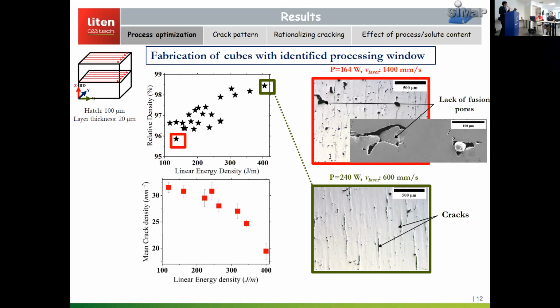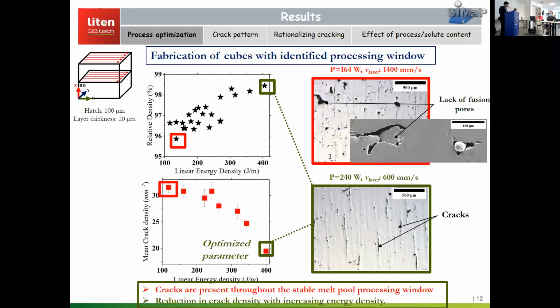So why not give more energy to the sample? Let me remind you, in the previous slide I said that if we give excessive energy, we can also end up getting instability conditions. So the optimized parameter here corresponds to the parameter where we found the maximum relative density, but still cracks were produced.